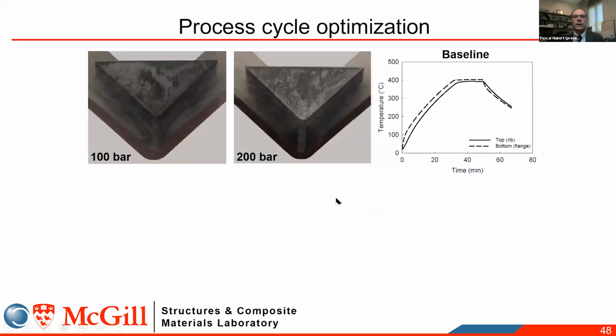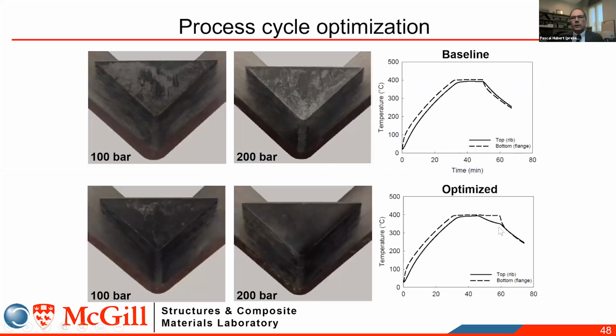The idea here is to use this simulation to guide you towards the design of the tooling and the process. To show you here the example of how you can play with the process, I'm showing you first the temperature profile of the top and bottom tool that follows the same trend. What you can end up with is a poor quality of the rib, even if you put more pressure, because putting more pressure will not help in that case. What you need to do here is to do a different temperature cooling profile from the top and bottom. And that was developed through the use of these models.